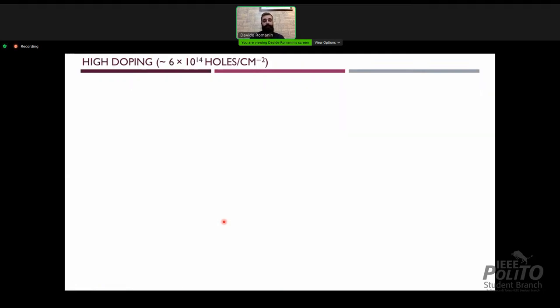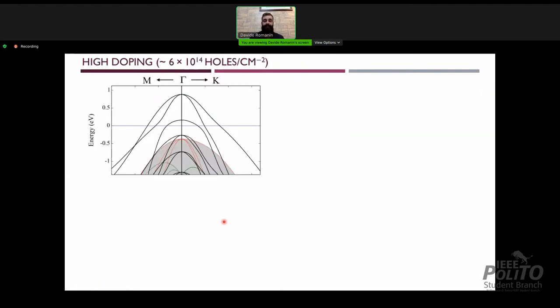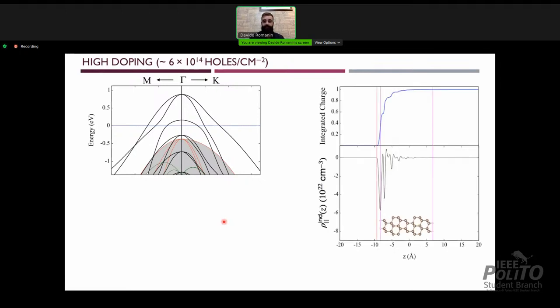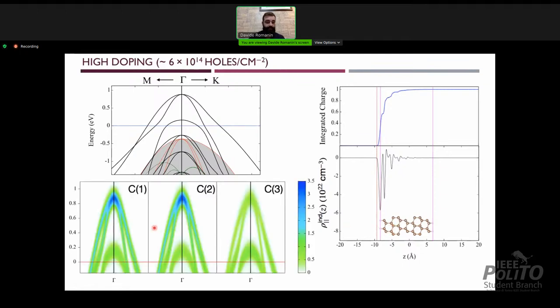Finally, at high doping, the system again is completely surface-like. The charge fluctuations are strongly localized around the first two carbon layers, and indeed the highest contribution at the Fermi level comes from the first and the second, while the third is just one half with respect to the other two. However, a superconductive phase transition couldn't be located for low and medium dopings, but only for high dopings.